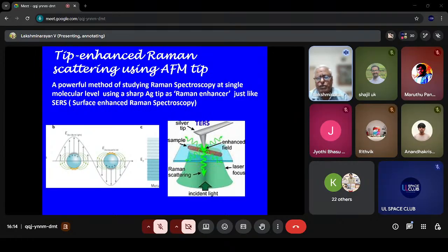But then a phenomenon was found where certain materials with certain refractive index and dielectric properties, like silver, when roughened, enhance the Raman spectral strength by several orders of magnitude, sometimes even a million times more. A typical example initially studied was pyridine on electrochemically roughened silver. That was there, but there was a lot of work going on. And in fact, Raman spectroscopy has become a very handy instrument for forensic studies and other things. They all use surface-enhanced Raman only.